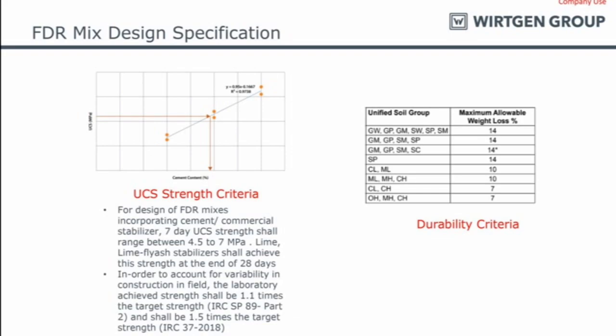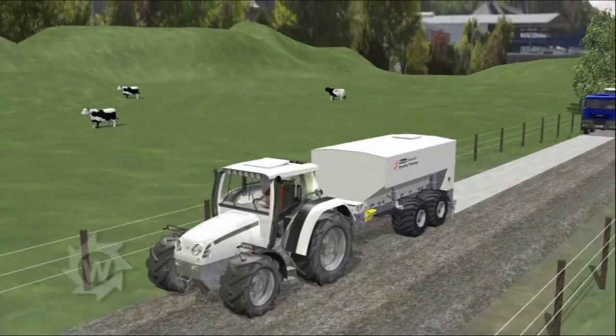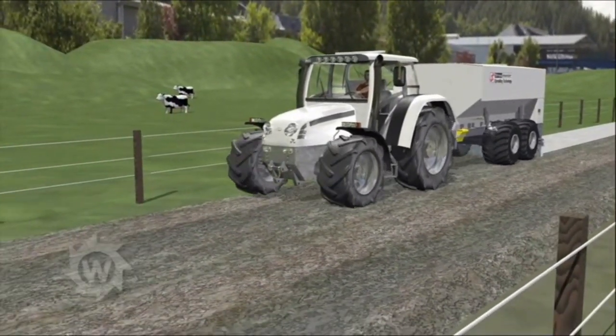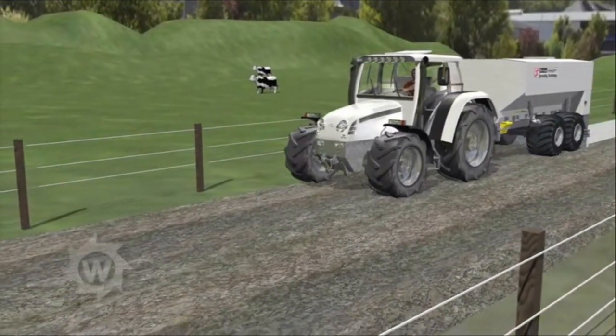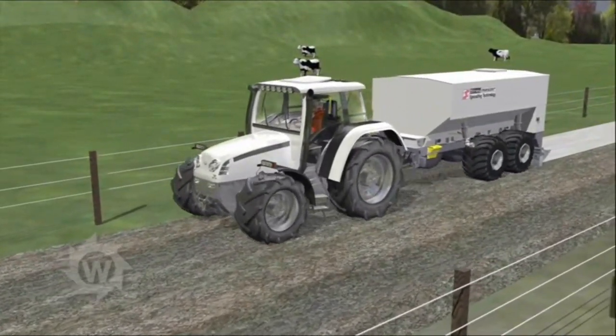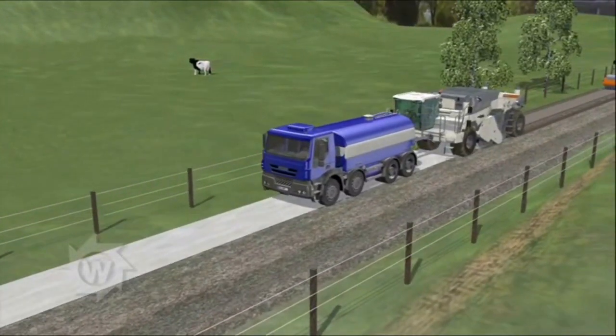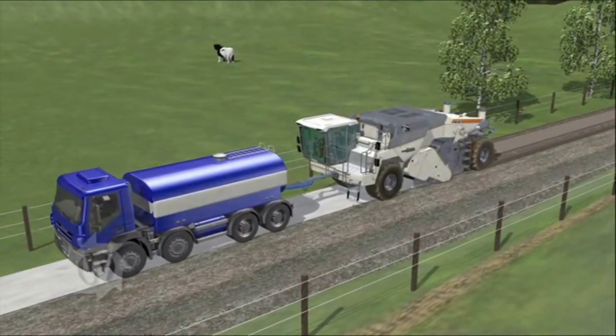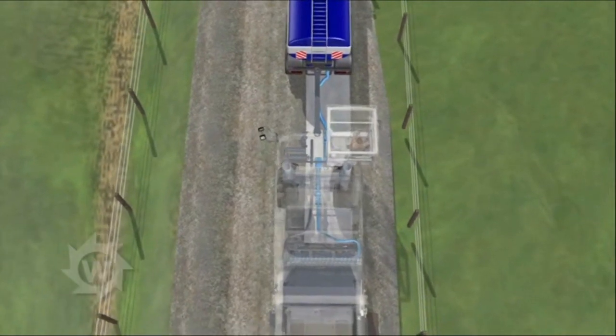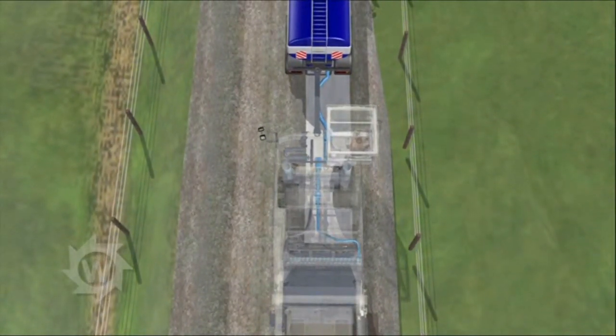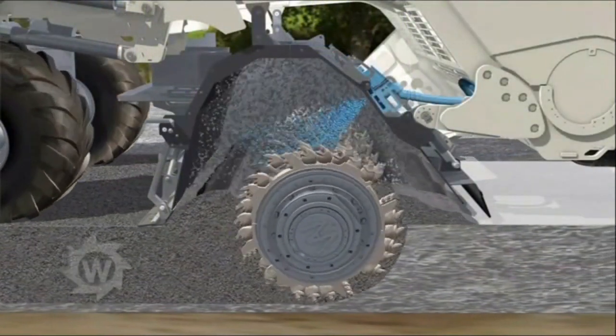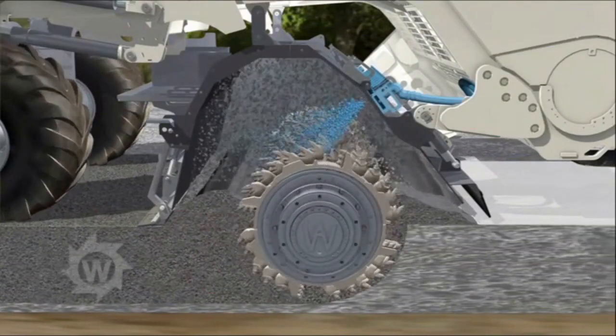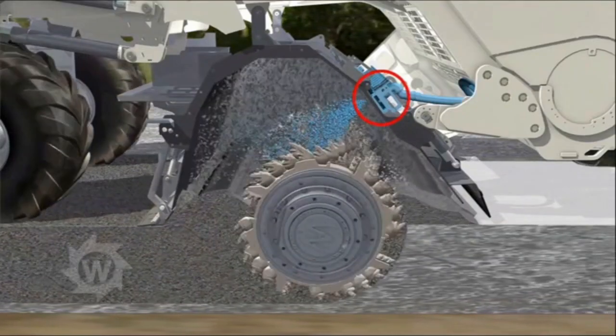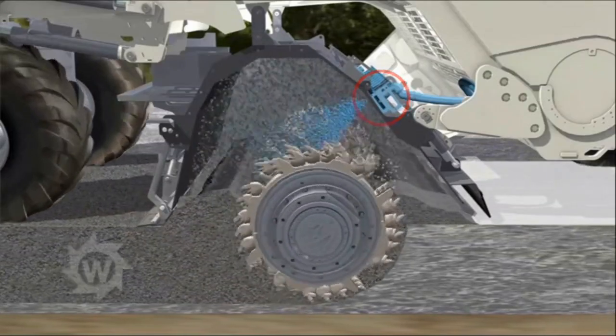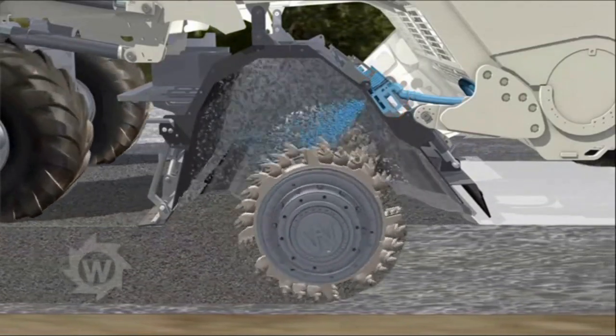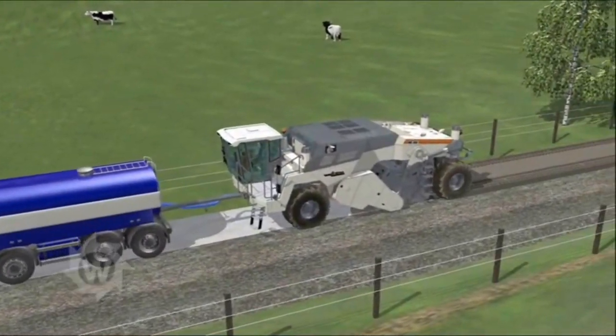Here is a small animation of this FDR process. To produce a new hydraulically bound base layer, a towed spreader from Streumaster pre-spreads cement. Computer-controlled metering feeders ensure highest spreading accuracy. Behind the spreader, the Wirtgen recycler pushes a water tanker truck by means of a push bar. The recycler draws in water continuously via a hose connection. The powerful milling and mixing rotor mixes the existing material and pre-spread cement to produce a homogeneous mixture. At the same time, the required amount of water is injected into the mixing chamber via a microprocessor-controlled injection bar. The pressurized scraper at the rotor plate levels off the recycled material to create an even surface.